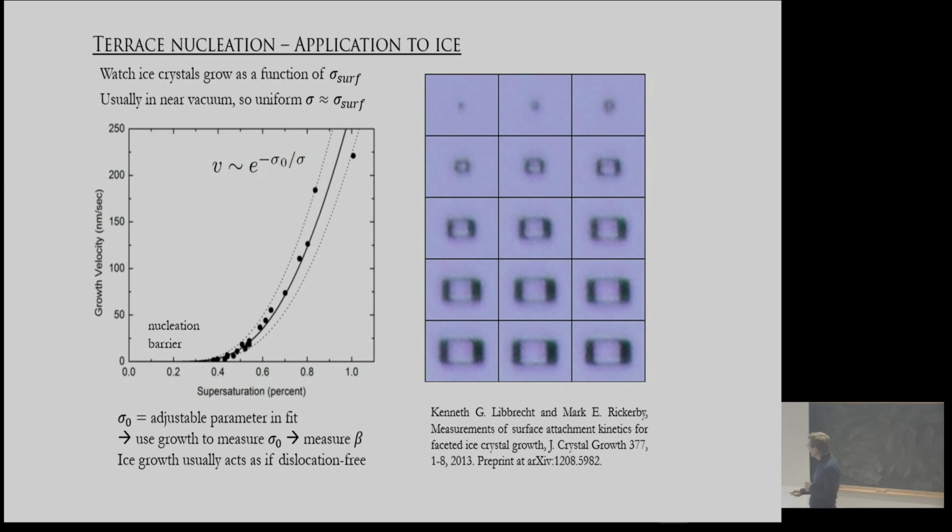And there it is. This curve has this functional form to pretty reasonable accuracy. It's certainly not linear or anything like that. It fits really nicely to that. So we have a theory, and it seems to work. This sigma 0 is an adjustable parameter, as is A, but in terms of functional forms, it fits nicely. If you measure this sigma 0 by doing a fit, you're basically measuring the step energy. So we can extract the step energies from these measurements, and that's usually how one measures the step energy.